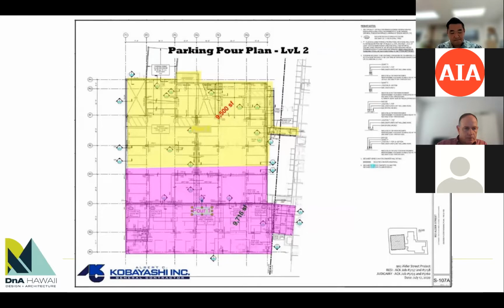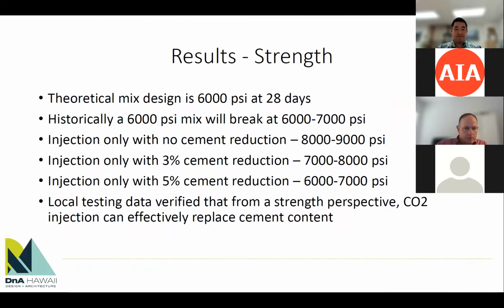Okay. So here's the results. Next slide. We measured a lot of data throughout this project from a testing perspective. So the typical mix design, 6,000 PSI at 28 days. If you were to test that, it's designed a little conservatively, so you would see the 6,000 mix breaking at 6,000 to 7,000 PSI, somewhere upwards of 6,000, of course.